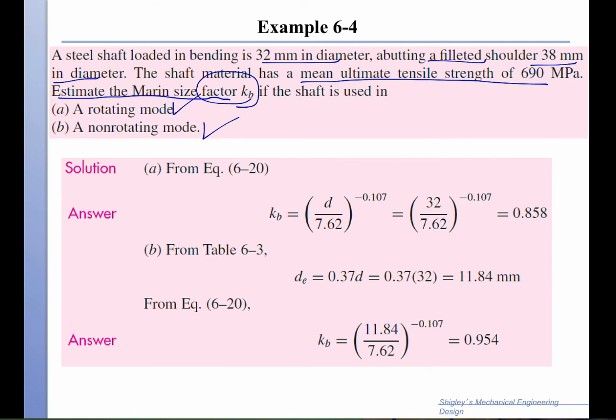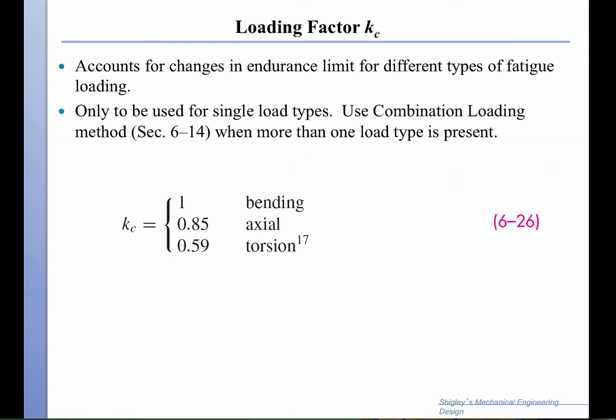If we use the rotating mode, then we would find k sub b directly, because it's in millimeters, so we use d over 7.62, with the same coefficient here. Then we get k sub b equals 0.858. In the case that we have a non-rotating mode, we have to use the equivalent diameter and use the same formula, and it gives us 0.954. After that, we have a load factor, and the load factor, as we mentioned, is 1 for bending, 0.85 for axial, 0.59 for torsion.